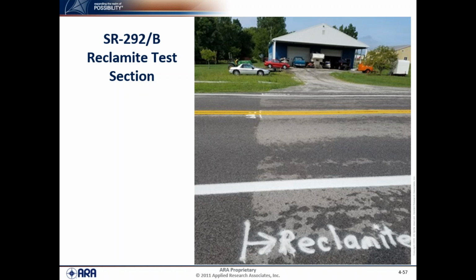And this is on 292 location B, north of East Liberty. This is the transition area, the untreated area. When Reclamite put theirs out, they had that paper they put down, so there was a definite transition, and we're still seeing that definite transition. How much it's drying out faster, I don't know, but the surface is drier relative to the adjacent section or transition that had no sealer applied to the surface, okay? So the surfaces appear to be drying at different rates.